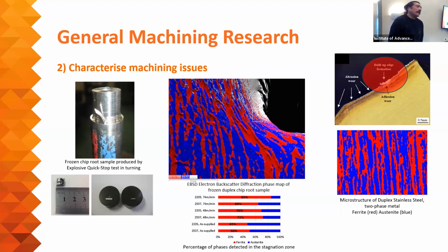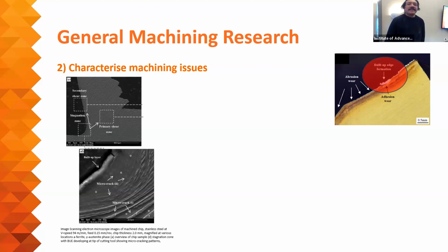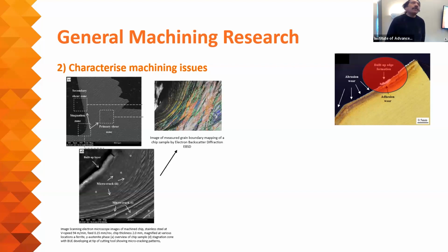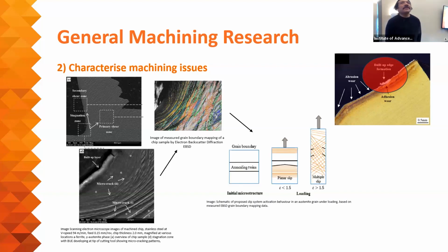So this was an experimental observation. In here you can see running through a phase map. That's what the original microstructure count looks like, and there are clearly larger counts here. So I took that observation and went, this might lead me somewhere, hopefully. And did some more observations using scanning electron microscope. Did some more EBSD beam time, counting up misorientation angles.